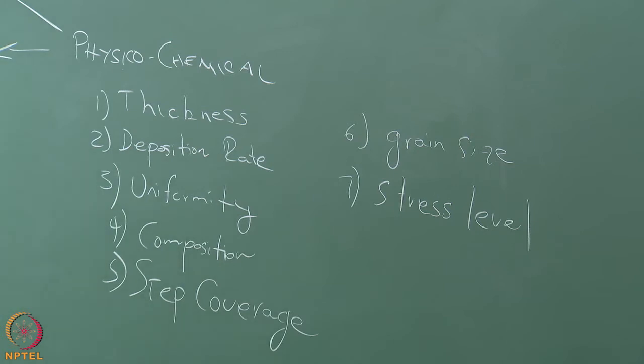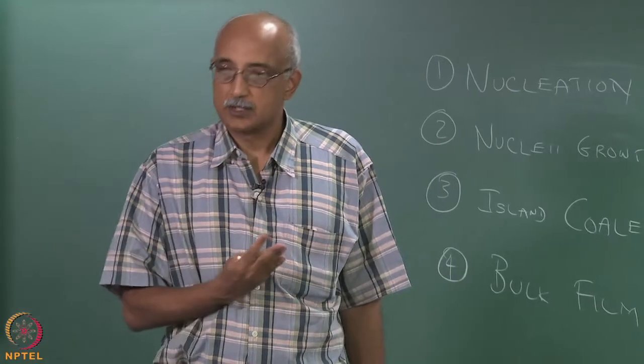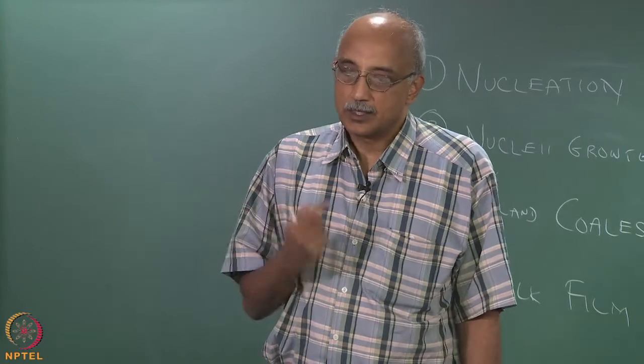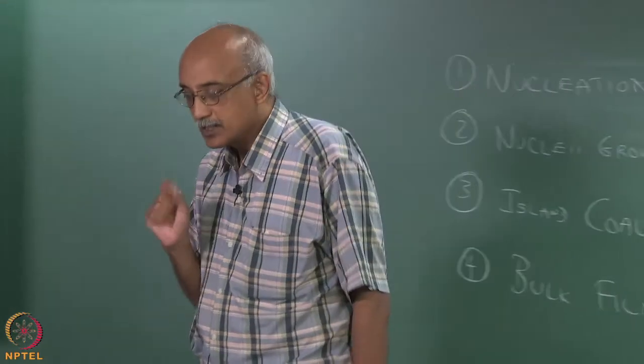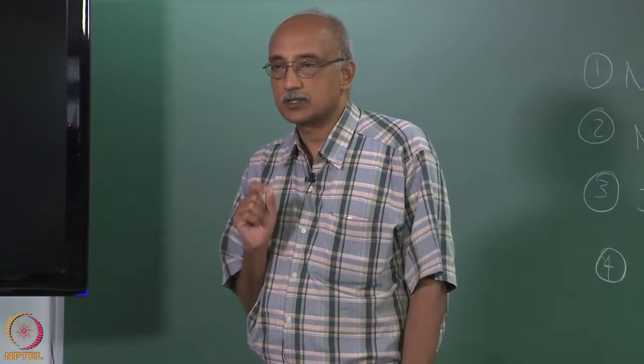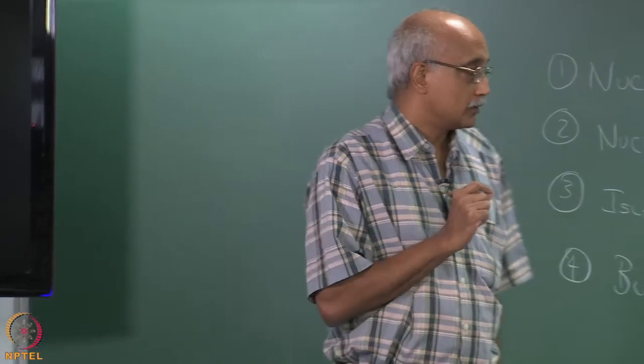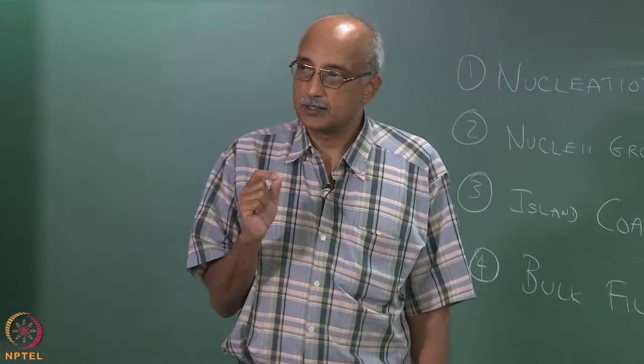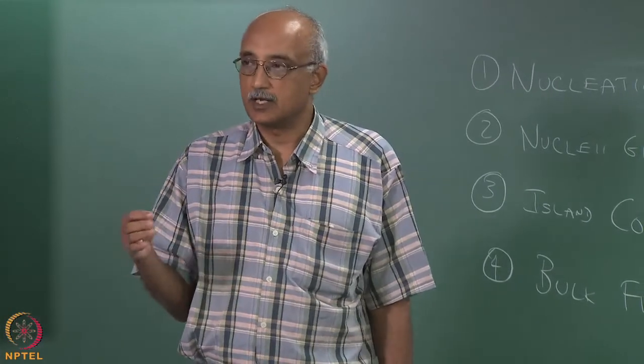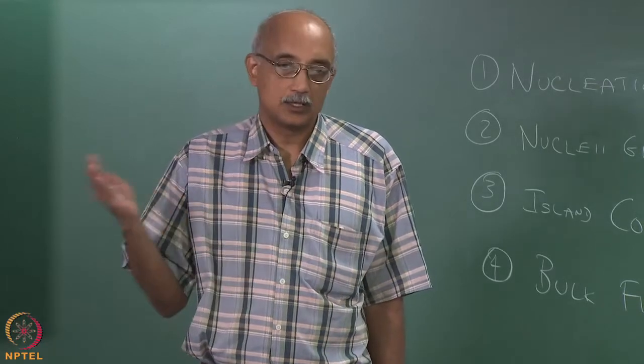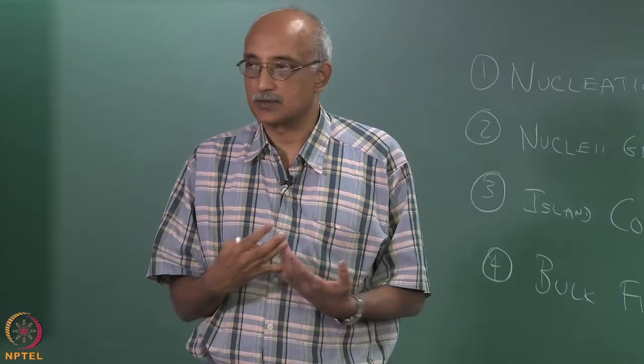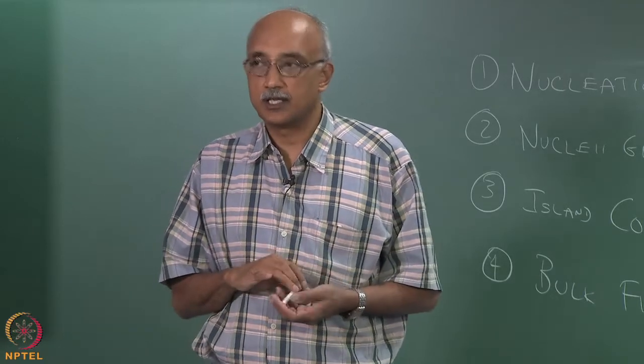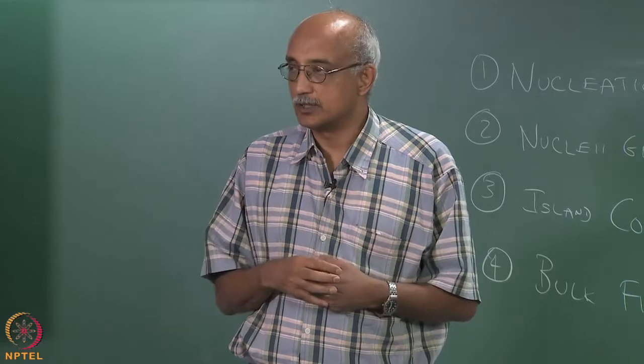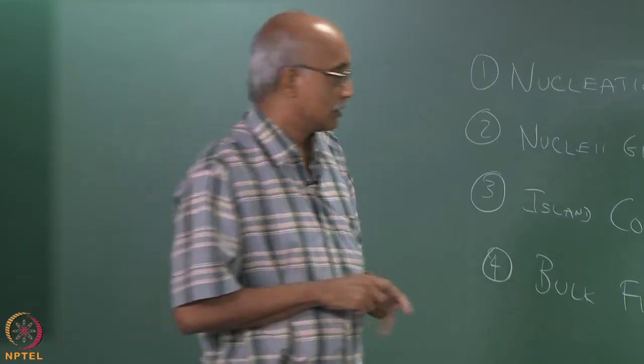When a film is subject to compressive or tensile stress, it can crack. So the susceptibility of a film to cracking or other types of stress-related disorders is very important to characterize as well. Now, what controls the stress level, again, is the grain size. The coarser the grain, the more likely it is that the film will be affected by various stresses that are present on the surface. A fine-grained structure enables a much more robust film to be realized on the surface.